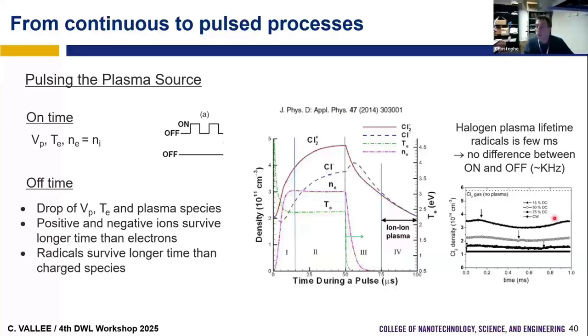So that's why I'm saying that when we pulse, usually we don't really modify the radical flux, because radicals can survive a very long time, for example 50 milliseconds. And usually the pulse we use for the process is about 10 kilohertz or 1 kilohertz. So at the frequency of the pulse, radicals survive during the off time, so the radical flux is always constant, even when we don't have any power. But as we pulse, we can lose the ions and the electrons. So if we lose the ions, it means that the ion flux will be modulated and we'll have less ion flux during the off time compared to the on time.